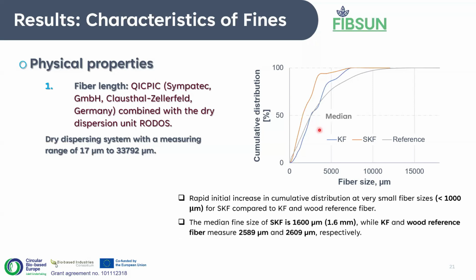And what we find, just looking at this image here, is that with the super short, which I call SKF, you see that the median fiber length is the shortest. When we look at the median fiber length of the short fibers, it's almost about the same as the reference wood. Of course, aside from the median, the reference wood still has longer fibers. And the goal for us is to see how this fiber length will influence the final product. Which brings us back to the point of not achieving the target thickness and target density. This is one of the reasons why we could not achieve that for SKF, because the fibers are too short. And for that, it would require a different approach or increasing target density or whatnot.